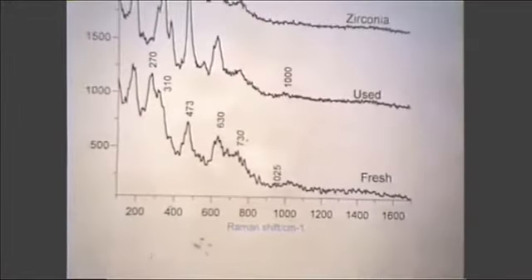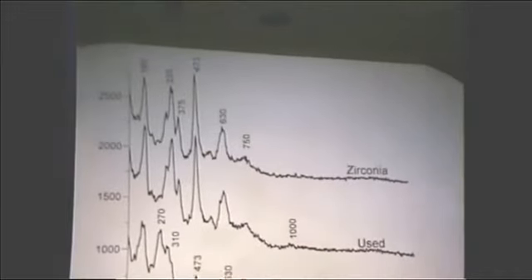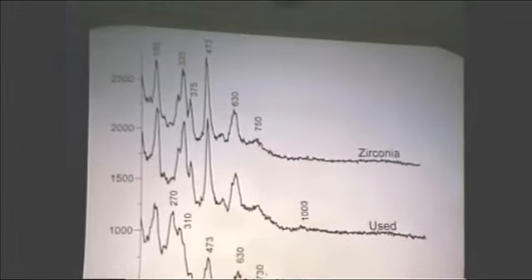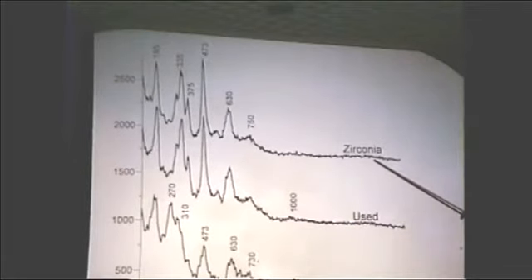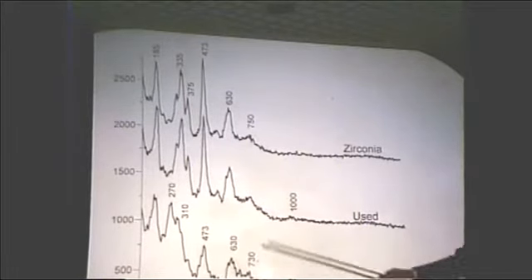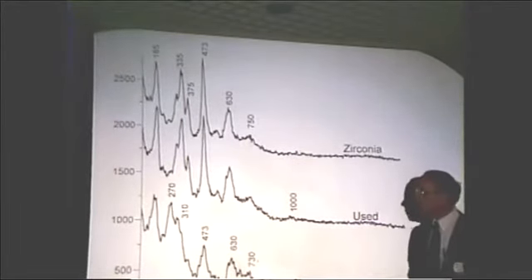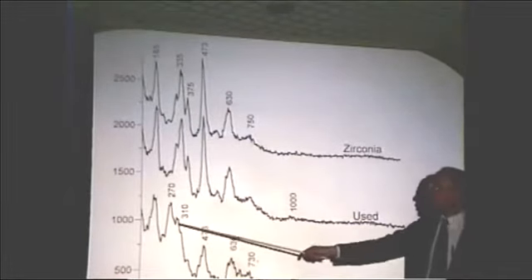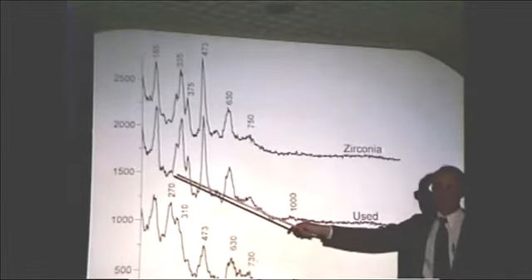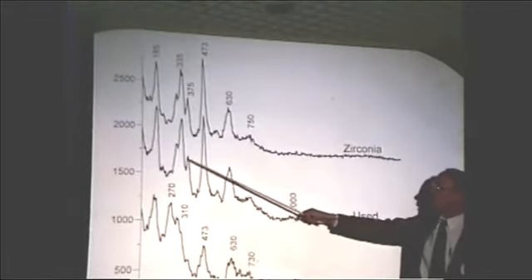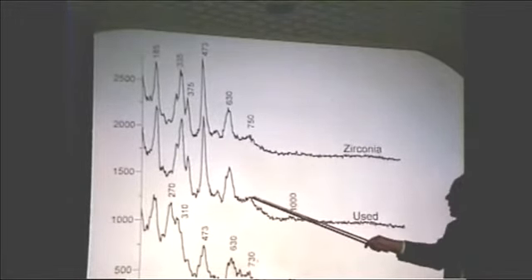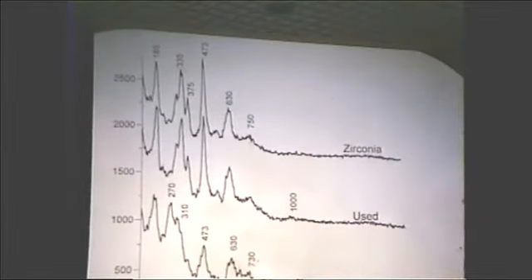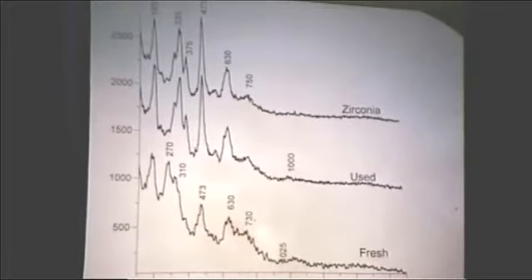The data now are very convincing, at least in terms of the fresh and used catalyst that he provided us with. This is monoclinic zirconia. This is the used catalyst, and this is the fresh catalyst. In particular, there's a band here at 270 wave numbers, which is only present in the tetragonal form, and you see quite clearly that it goes away in the formation of the used catalyst, and that we get essentially precisely the same pattern of peak intensities that are observed for the standard monoclinic zirconia spectrum.